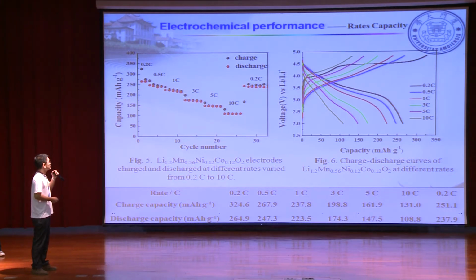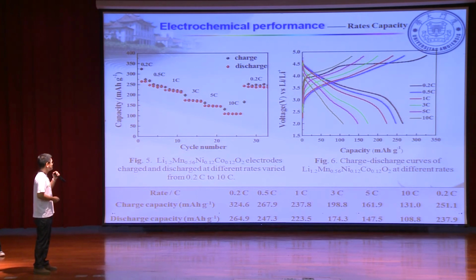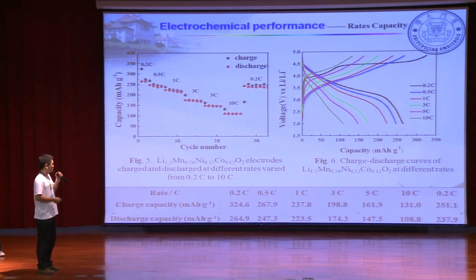Figure 5 and Figure 6 are about the rate capacity of LNCM, and at a low charge and discharge rate, our product has very high discharge capacity, and it could be 264.9 milliampere-hour per gram. And at an extremely high charge and discharge rate of 10C, our product also has 108.8. And then we decrease the rate back to 0.2C rate. The discharge capacity could be recovered to nearly the initial discharge capacity. And those data suggest a good rate capacity.